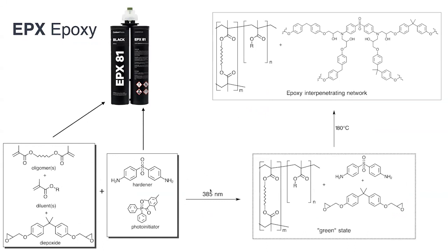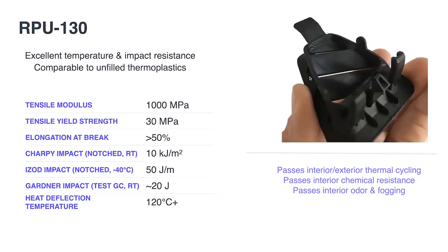We could print the part at 385 nanometer, set the shape of the part, and then have all this latent chemistry sitting there. And so this is basically a solid state polymerization in the form of a part to get amazing properties. And this works exceedingly well. You can make amazing materials. This is our RPU 130. It's a rigid polyurethane with a TG close to 130 degrees. It's very ductile.